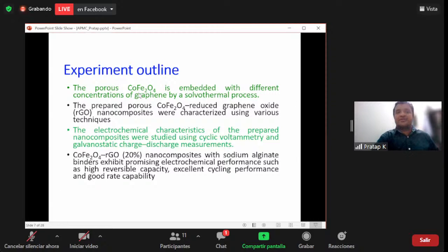So porous cobalt ferrite with different concentrations of graphene is synthesized by the solvothermal method. Since we want to check the effect of graphene, we thought we'll make the composite of RGO plus cobalt ferrite with different percentages. First, 10% RGO and 90% cobalt ferrite, 20% RGO and 80% cobalt ferrite, 30% RGO and 70% cobalt ferrite, 40% RGO and 60% cobalt ferrite. So we made 5 different samples and tried to check how they behave.